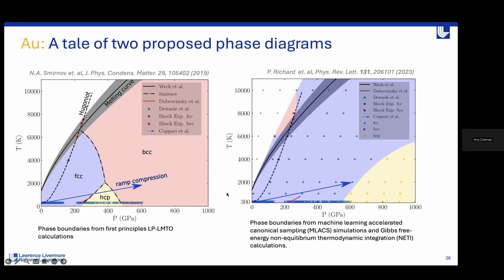Contrastingly, there's also a description of the gold phase diagram as maintaining its FCC structure up to about 600 GPa and then transitioning to an HCP structure. Something that both of these models have had to take into account is the fact that we know that on the Hugoniot, the gold does transition to a BCC structure before melting - we have experimental data that shows that unambiguously. In this model, it's addressing that by saying perhaps in the high temperature portion, we're creeping into the BCC phase with the Hugoniot before we melt. In this version, we're talking about more of a high temperature pocket of a BCC phase. So two different ways of addressing that.